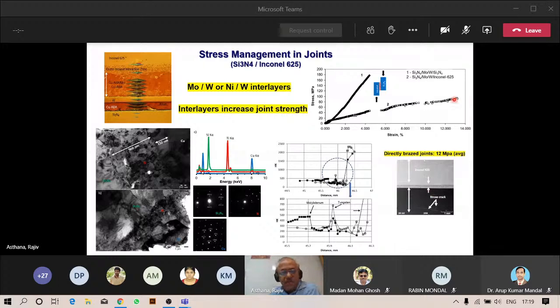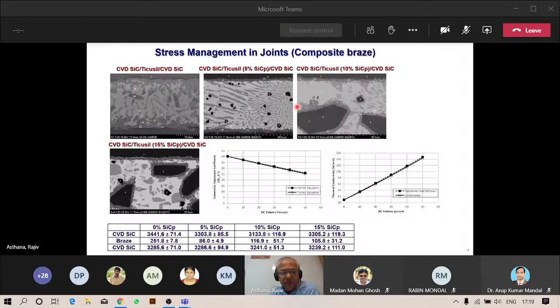Another way that we looked at was using a composite braze. And again, a lot of people have worked on this. So instead of directly bonding to the substrate using a braze, you could actually create a composite. In this case, we are looking at silicon carbide powders added to a silver, copper, titanium braze, in different percentages, and that is used for joining the ceramic. So the advantage here is that by putting silicon carbide in a high expansion braze, you are able to reduce the expansion coefficient of the braze and bring it closer to the bonded surfaces. And the other advantage is that you expect the conductivity to increase.